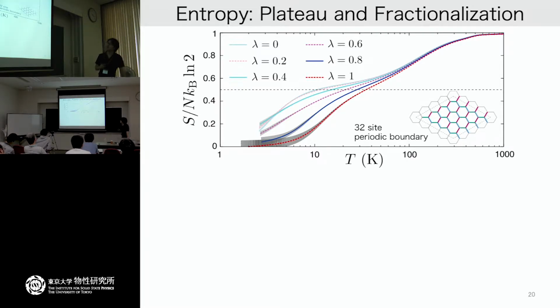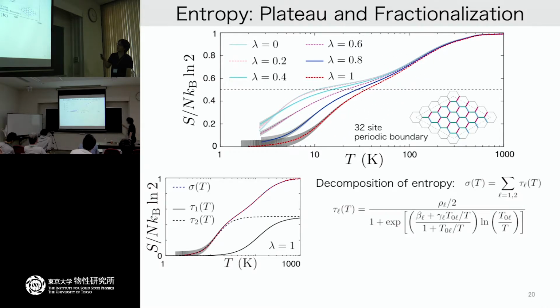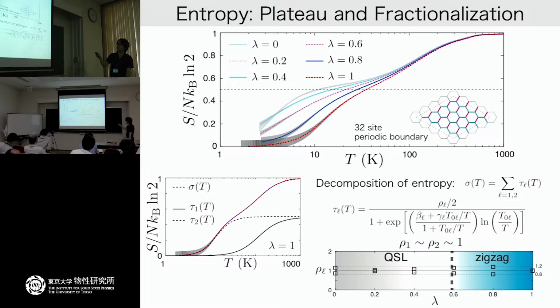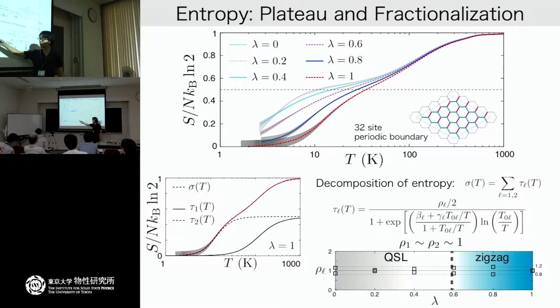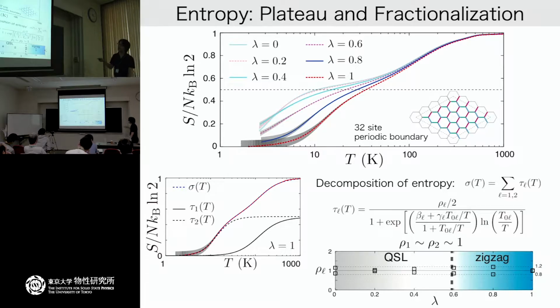And if you calculate the temperature dependence of the entropy, then we always have a shoulder-like structure, from the Kitaev limit to the ab initio limit. In the ab initio limit, it's not so visible, but we can divide this entropy into two parts, and analyze the weight of these two parts. From the Kitaev limit to the ab initio limit, the weight ratio is around 1. This means that these two separated entropy parts have more or less the same weight. This means that from the Kitaev limit to the ab initio limit, there is some finite temperature fractionalization of the spin degrees of freedom, even if we have a magnetically ordered ground state on this side, the zigzag order.